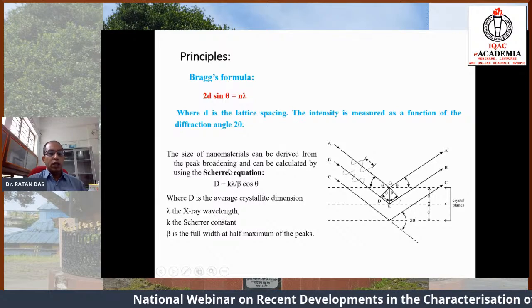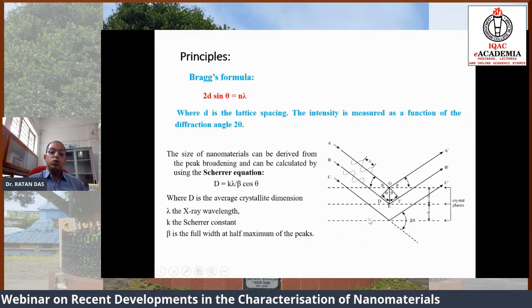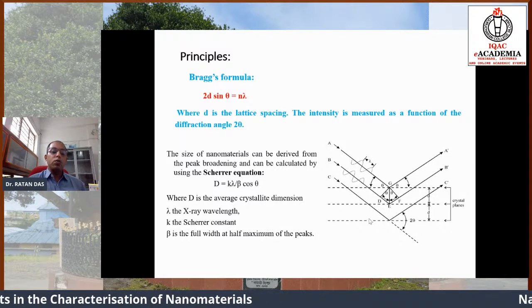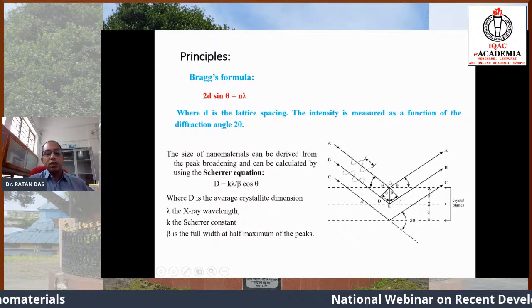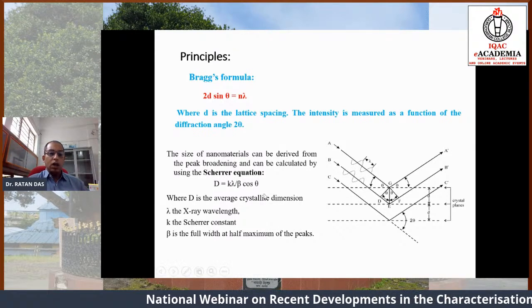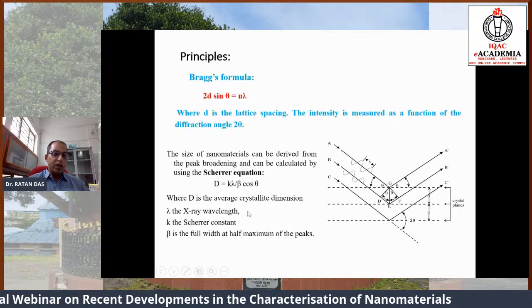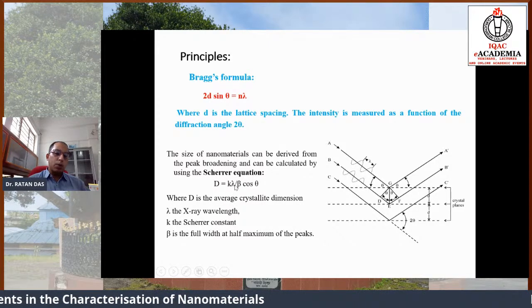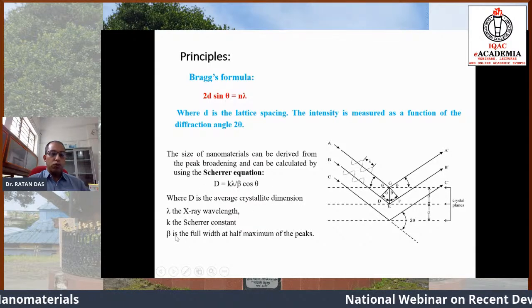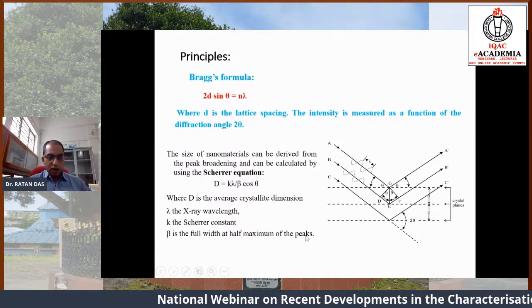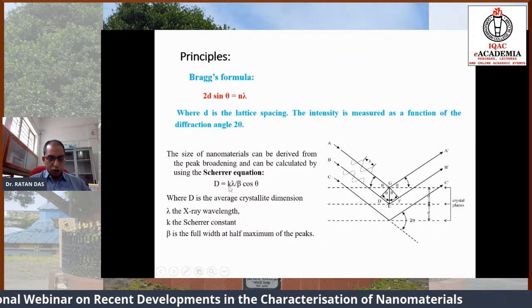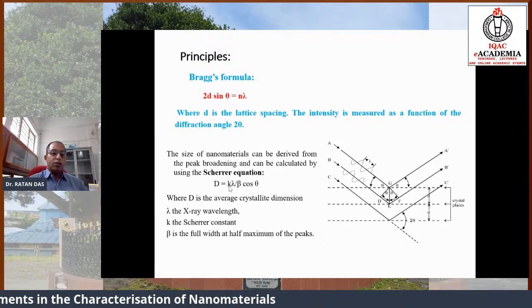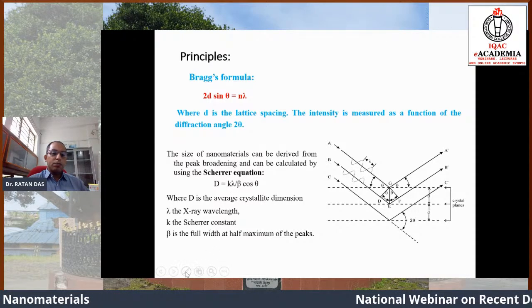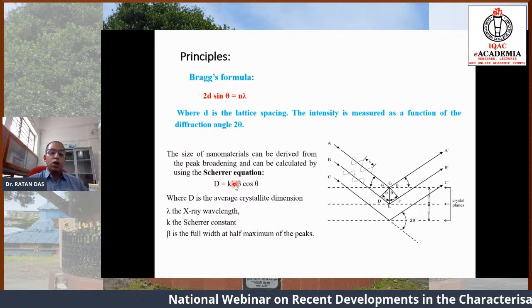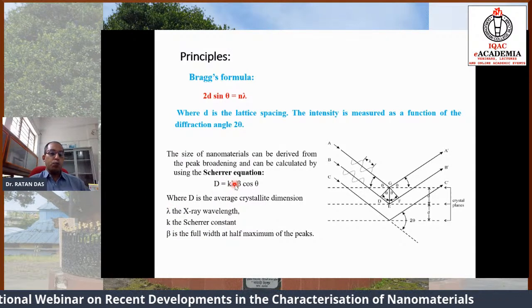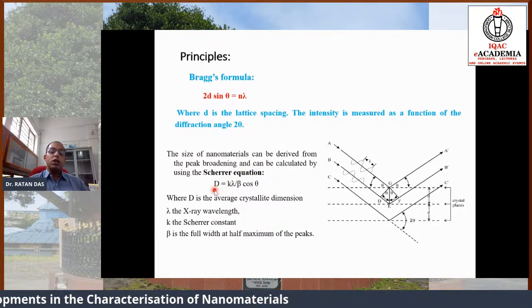Lambda is the X-ray wavelength. Here, in the X-ray diffraction pattern, we use X-rays of a particular wavelength. But I shall explain later. In some patterns we shall use a varying wavelength, but generally we use X-rays of a fixed wavelength and put in the value of that wavelength. Beta is nothing but our full width at half maximum, which I shall explain in my subsequent slides. And K is the Scherrer constant, which depends on the shape of the particle. If it is spherical, then we use approximately the value 1, or 0.93, or 0.9. And putting all these values, we can obtain the nanoparticle size.